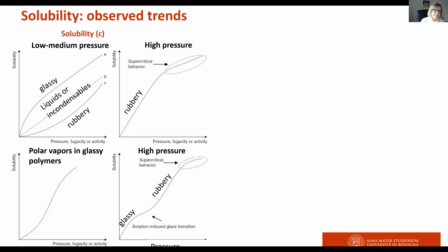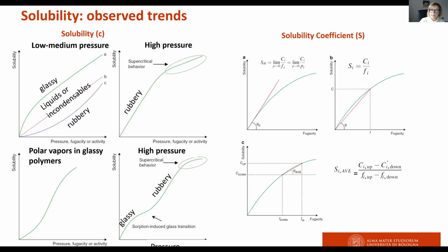You can also see sigmoidal shaped isotherms in the case of alcohol absorption in glassy polymers. And you can also see a transition induced by the sorption of the penetrant from the glassy to the rubbery state during your experiment. The solubility coefficient is the ratio between the concentration and the fugacity, and you can have an infinite dilution value or an average value depending on which point you are focusing on the solubility isotherm.